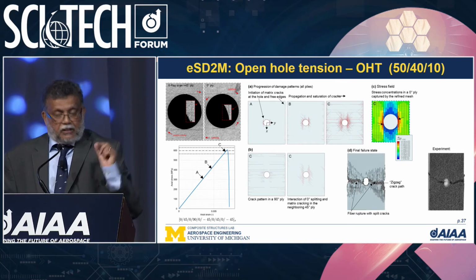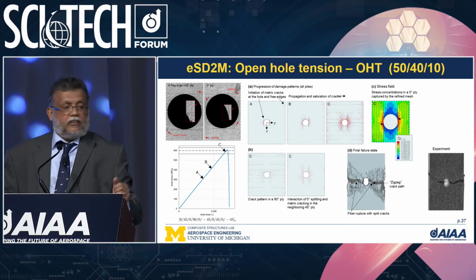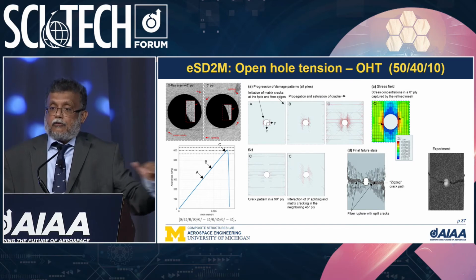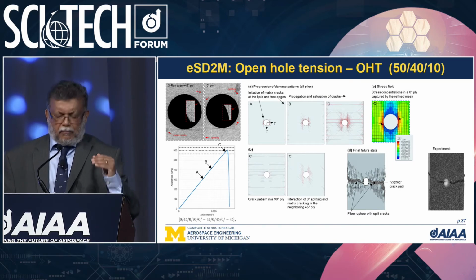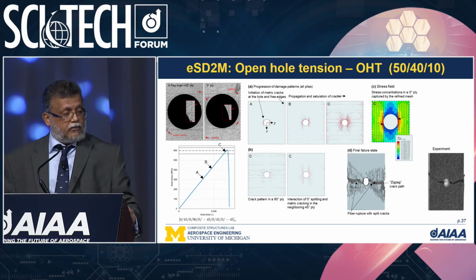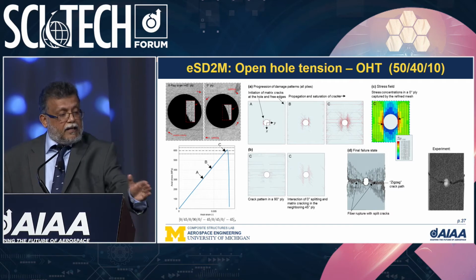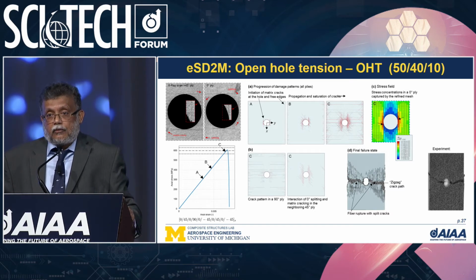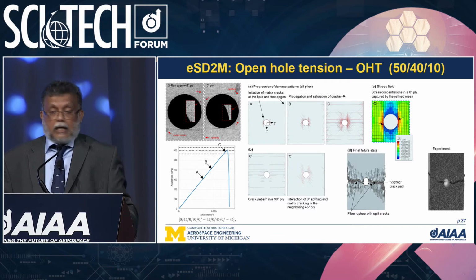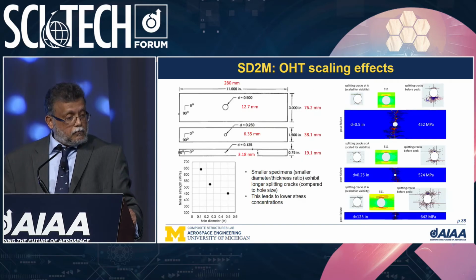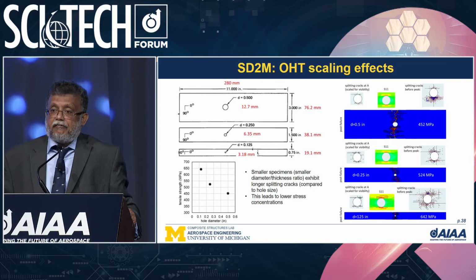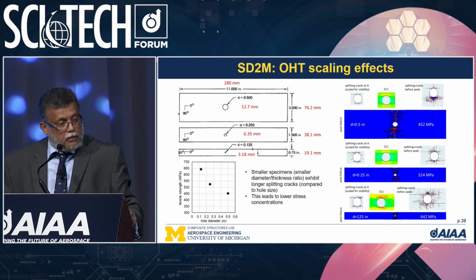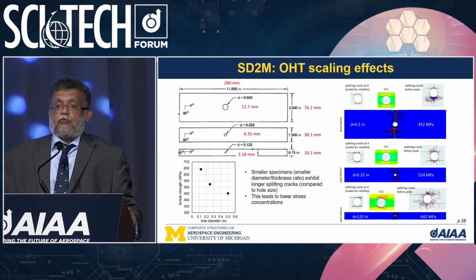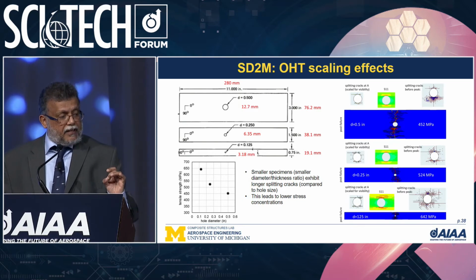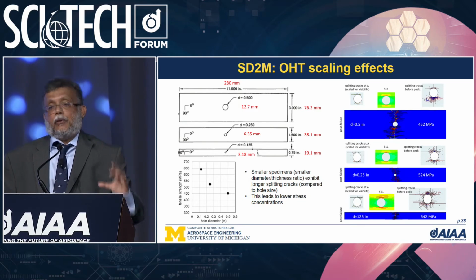We have captured the angle cracks, the splits in the zero plies, the transverse cracks, macro cracks, splitting cracks in the 90 plies, and finally the way the laminate fails. These were blind predictions that we did for these types of laminates. We did this as a function of the size of the hole to the width of the laminate, as well as keeping the hole size fixed and changing the width.